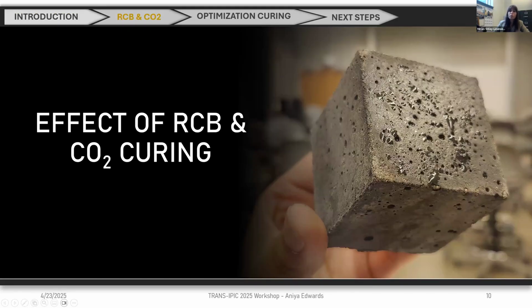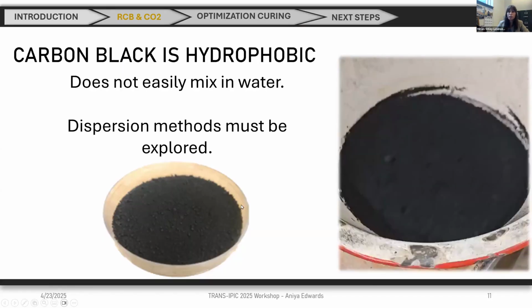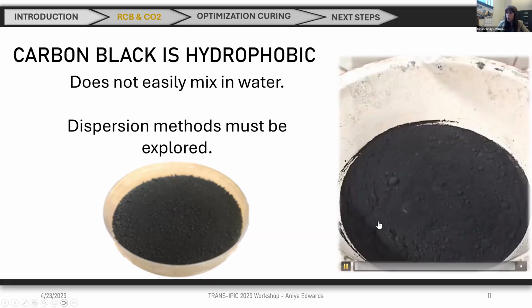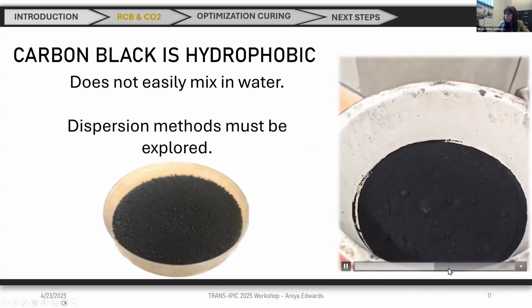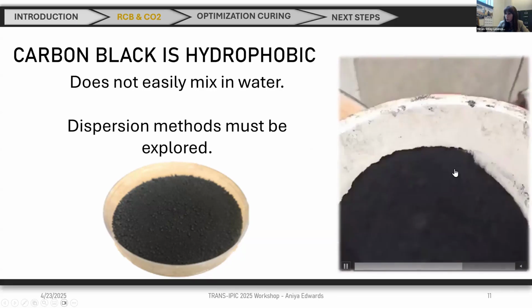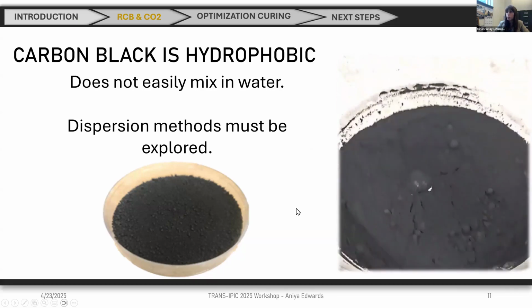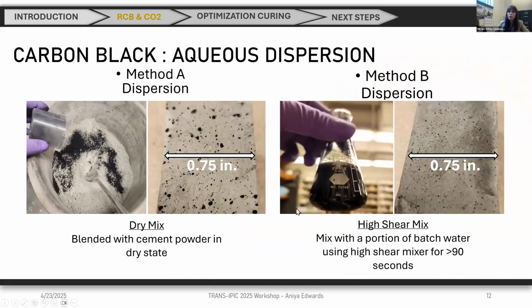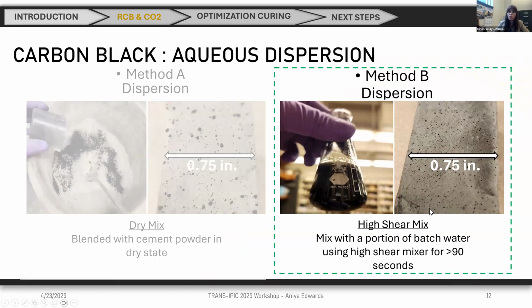So regarding the effects of recovered carbon black and CO2 curing together, well, this is the carbon black that we use. It's very hydrophobic. In the video, I think you will see that it's not mixing very well. It's not mixing with the water. It's just floating around. So that's why if you try to do it dry, that will not work. And we have to first disperse it into the mixing water with a high shear mixer. So that's something that we have to consider.